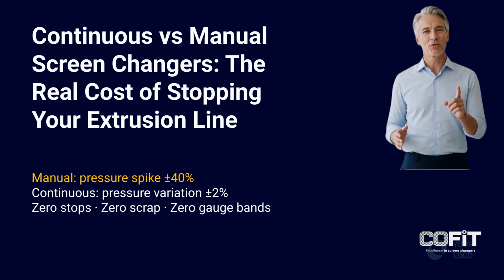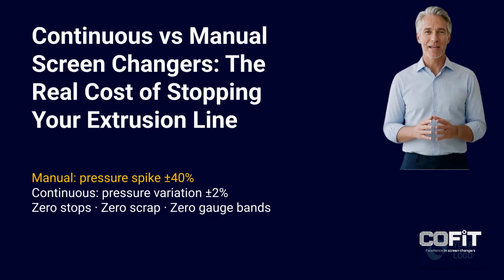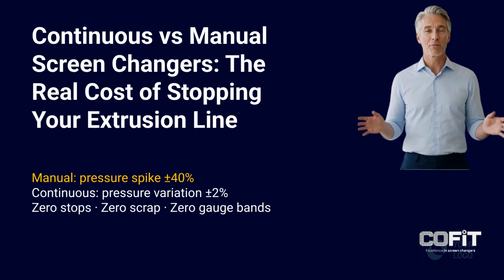A continuous screen changer eliminates these problems at the source. In a dual-cavity design, one cavity filters the melt while the second is being serviced. The switchover between cavities happens without stopping the extruder. Melt flow is uninterrupted. Melt pressure variation during the cavity switch is within plus or minus 2%. No spike, no drop, no gauge band, no scrap window, no filament break.